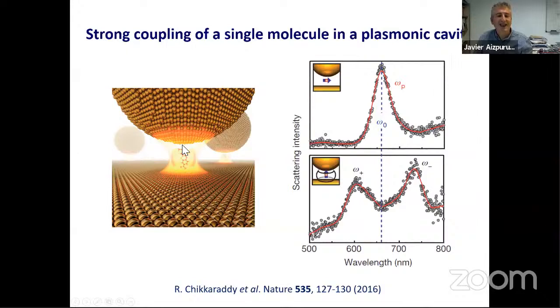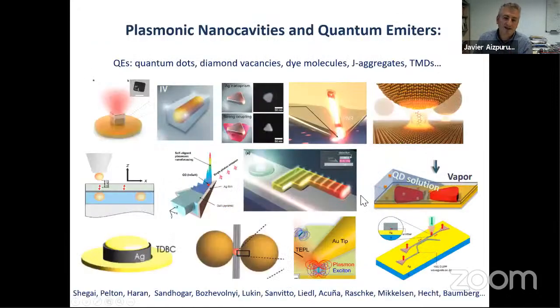And because of this alignment of the dipole pointing upwards and the local field in the plasmonic cavity, they managed to obtain the split in the two polaritonic branches in frequency spectroscopy, which identifies the strong coupling regime of a single emitter in a plasmonic nanocavity, right? And since then, a takeoff of exploitation of this plasmonic nanocavity has occurred, right?